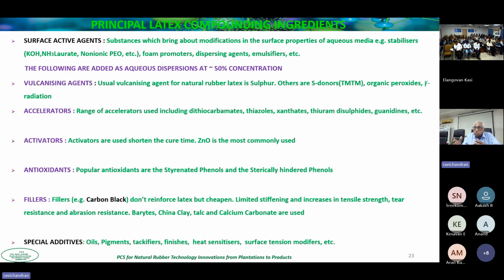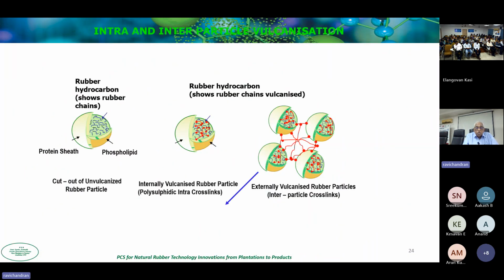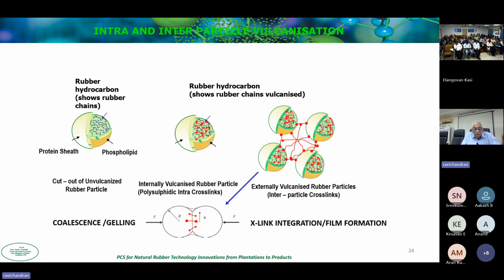Latex products usually have a very high rubber content, and it is not with fillers and not with process oils, and all these are not necessary because the processing does not require that. So here you see on the left-hand side, the individual rubber particle, which has a protein sheath, a phospholipid layer, and inside the particle, the rubber. So the rubber particles are protected by this protein sheath.